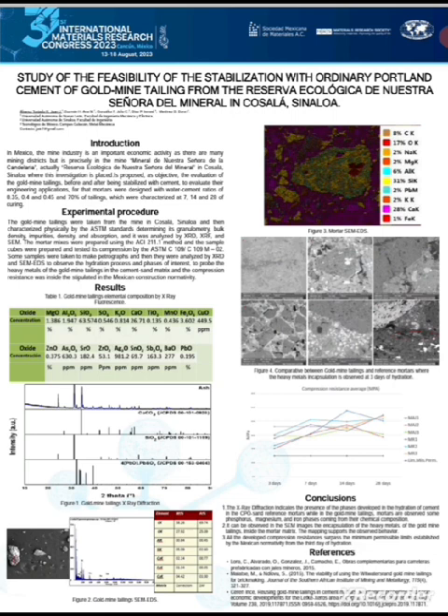The results were satisfying. The X-ray fluorescence XRF showed that effectively the gold mine tailings were contaminated with heavy metals like lead, Pb, arsenic, As, and barium, Ba, exceeding the limits indicated in the NOM-052-SEMARNAT-2005 for dangerous residues and NOM-141-SEMARNAT-2003 for maximum allowable limits of contaminants in gold mine tailings. So yeah, there was this material contaminating the ecosystem and affecting the health of the surrounding people as we supposed.